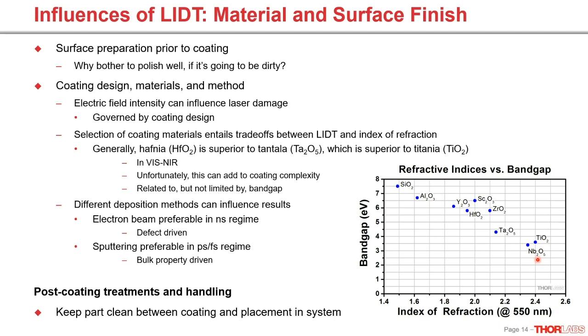As we briefly touched upon before as well, different deposition methods can influence your damage threshold results. You're typically going to want to use electron beam deposition if you're working in the nanosecond regime, because the nanosecond regime is defect driven, and you're typically going to want to use sputtering in the picosecond and femtosecond regime, because this is driven by the bulk properties of the coating. And you're also going to want to ensure that the part stays clean between the time it's coated and when you place it in your system.